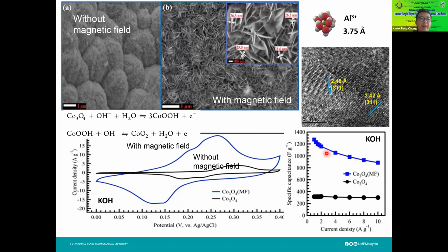You can compare it. If we do not use a magnetic field, all of them, even though they exist as the paddle, tend to clump together in one big nano flower. But under the magnetic field, we found that they actually try to align because cobalt is a ferromagnetic material. Each of these nano paddles has a thickness of about 25 or 26 nanometers, so we can visualize that it's a very high surface area material.